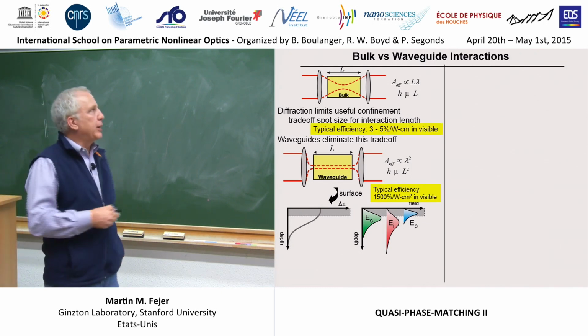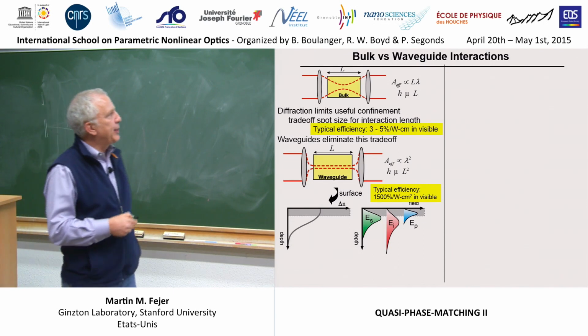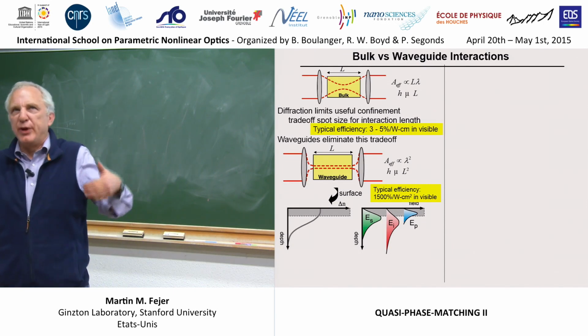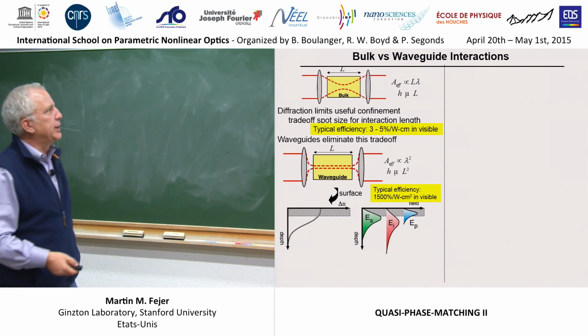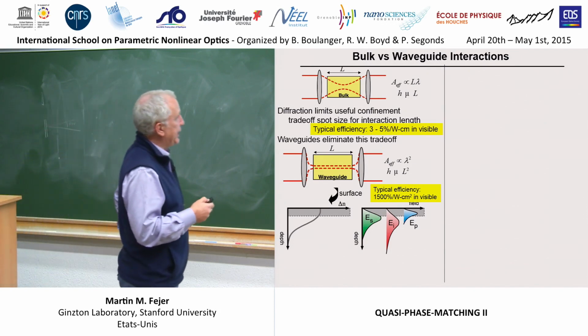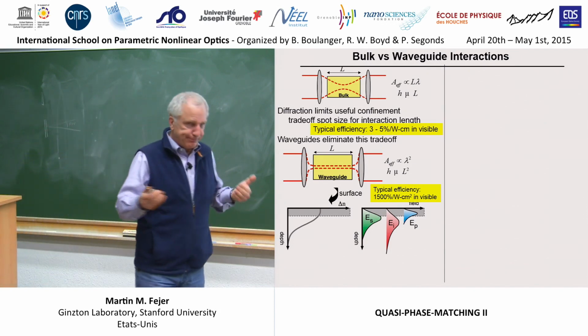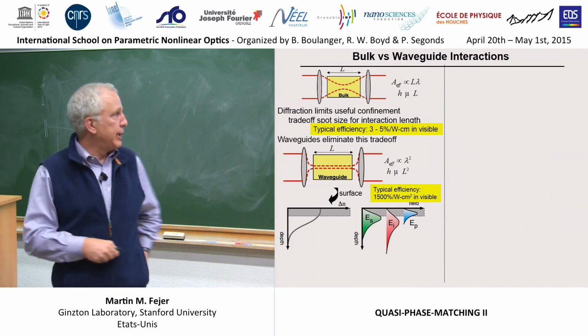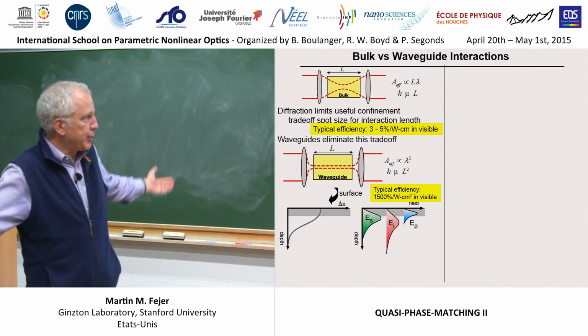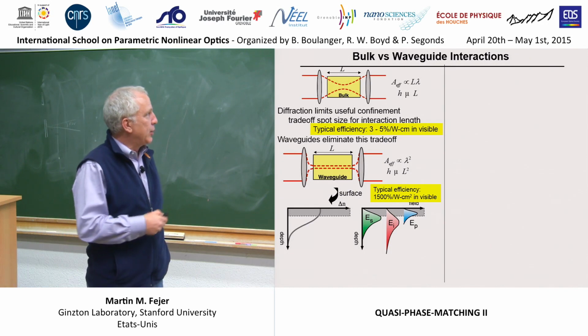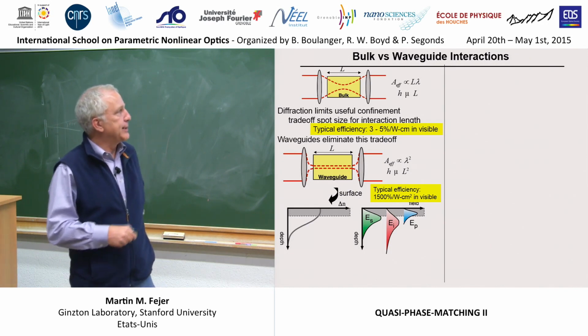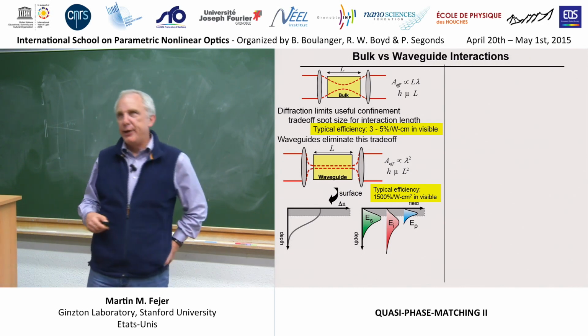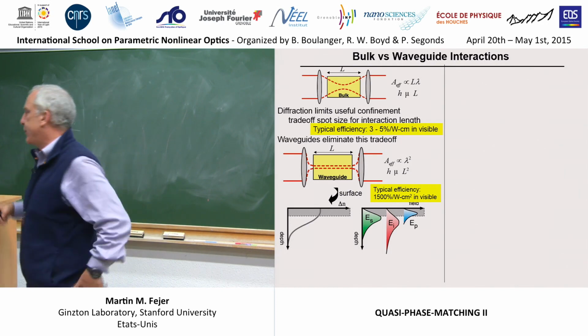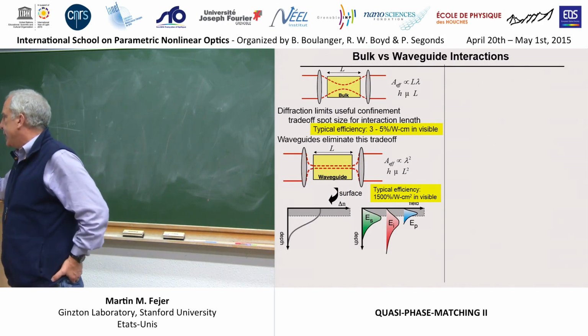If we compare a typical bulk quasi-phase matched medium in the visible for SHG, you might have a few percent per watt per centimeter efficiency in a bulk device, while a typical number in a well-designed waveguide is 1,500% per watt centimeter squared—enormously higher efficiencies, several orders of magnitude higher, as well as more advantageous length scaling in a waveguide.